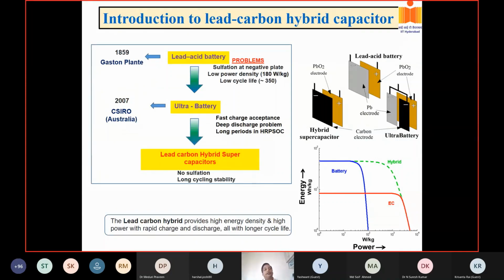So to overcome these issues, lead carbon hybrid ultra capacitors have come up. So what is done actually? The negative electrode of the lead acid battery is completely removed, and you put a carbon electrode of the capacitor. So it is no more a lead-acid battery. It's called lead carbon ultra capacitor. This is one way you can eliminate the lead sulfate formation completely.